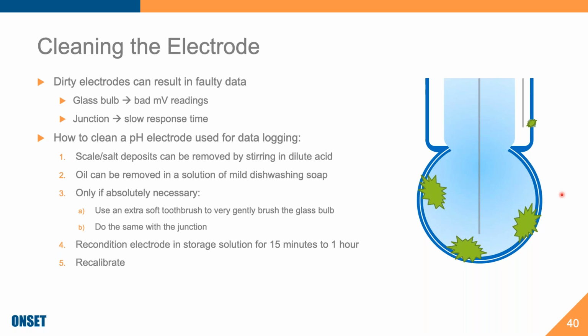To clean a pH electrode that you're using specifically for data logging, this is different than lab analysis since it's not presumably sitting too long in your sample. The first thing that you want to double check is that the scale and salt deposits that are on there, maybe from your salty sample, are removed using a dilute acid. You can use dilute hydrochloric acid, or even just vinegar and water, or just vinegar. That'll help basically dissolve those deposits. If for some reason there's oil around your glass bulb, so maybe you're monitoring in an oil spill, recognizing that pH is pretty much not accurate or repeatable in terms of measurements in non-aqueous solutions. But if there's oil on your glass bulb, then you can remove it with swishing in a mild dishwashing soap, keeping in mind again that this will require reconditioning afterwards.